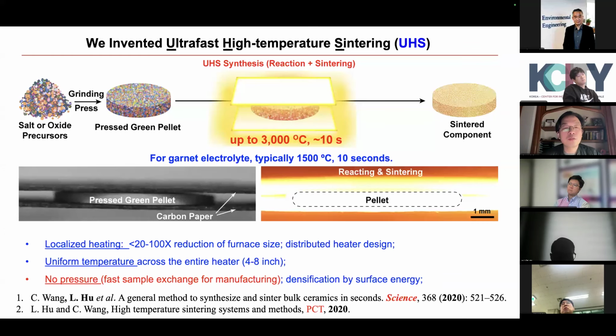So this is how the process looks. Not two steps, just one step, right? You have the pellet, you push it in, and you push it out. The whole thing only takes a few seconds. Actually, the principle in my lab is that everything has to happen in less than 10 seconds. That way, you don't get contamination. You don't have lithium loss. The lithium doesn't have time to evaporate.